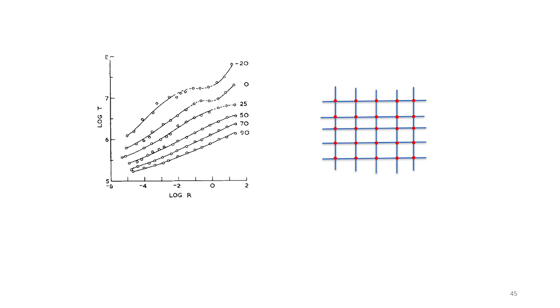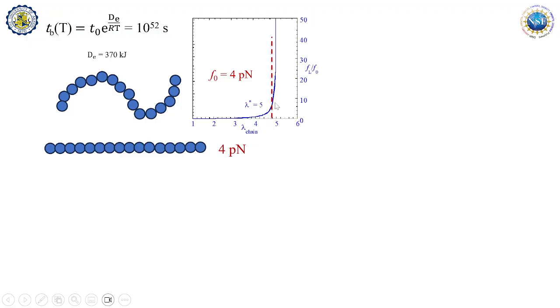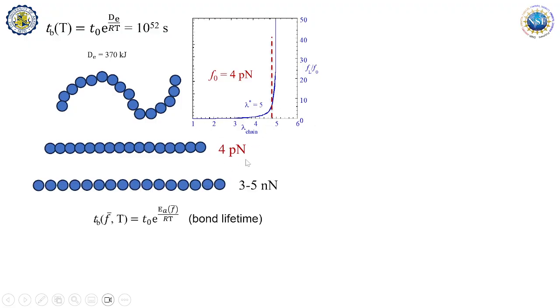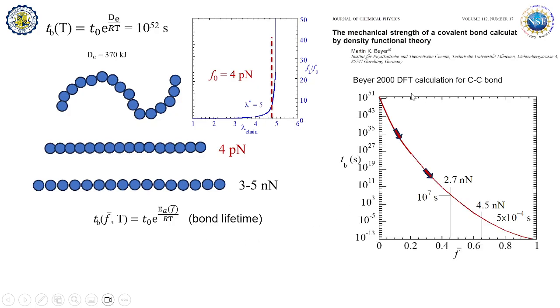So in any case, I think there's no question that the problem of fracture is a transition problem. And I'm going to flash very quickly. When the chain is stretched, you can build force. You can build more force. And if you don't build any force, the bond can survive longer than the known age of the universe. That's textbook. So you build enough force, and this is the density functional calculation showing that the lifetime of the bond just crashes down as more tension is built in the bond.